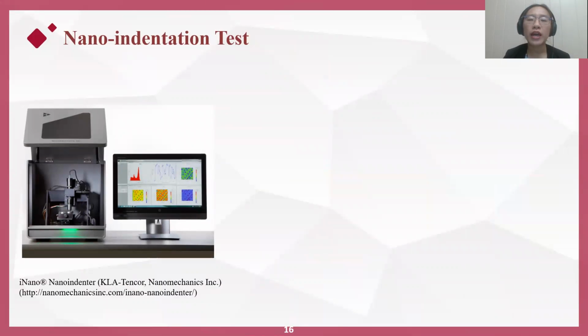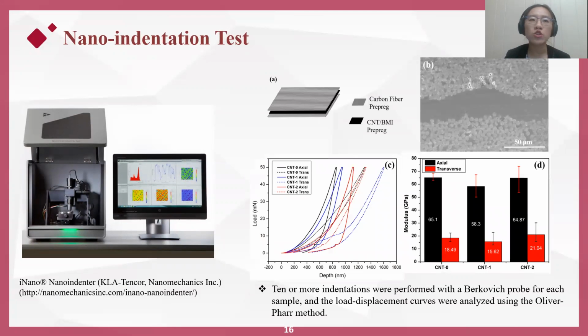To further study the mechanical properties of nanocomposites, we conducted nano-indentation tests to reveal more detailed microstructure-property relationships and to provide nanoscale insights of elastic modulus and indentation hardness. The as-collected CNTs were saturated in BMI solution and sandwiched in between the unidirectional carbon fiber BMI prepreg before curing. The carbon fiber prepreg was designed to provide support because this is a cross-sectional test.